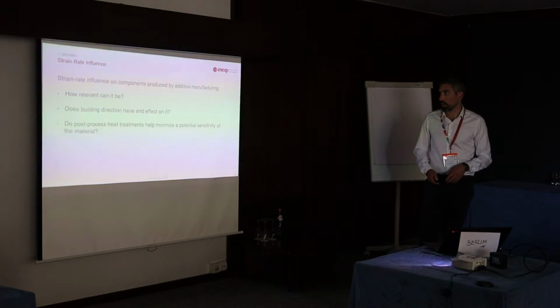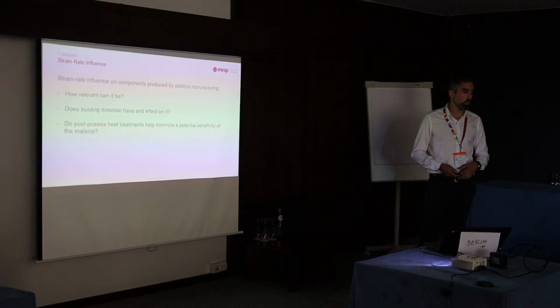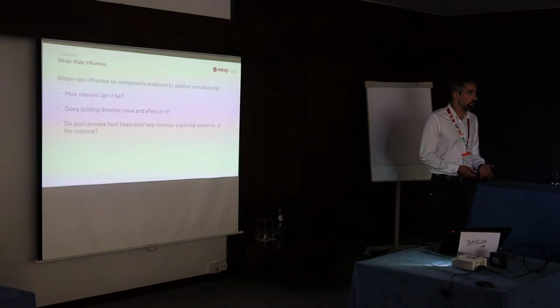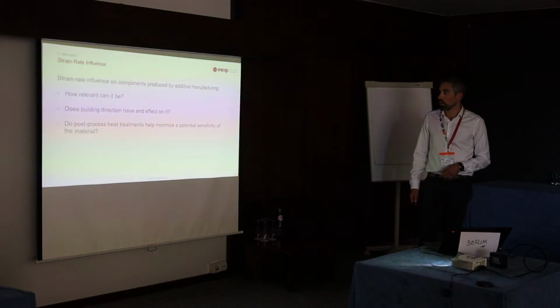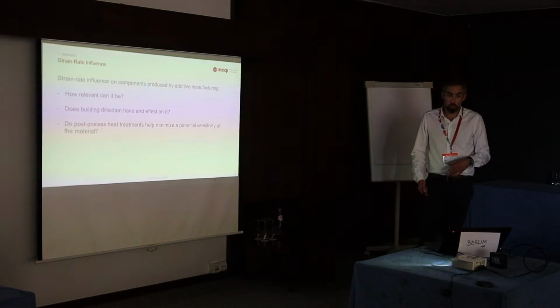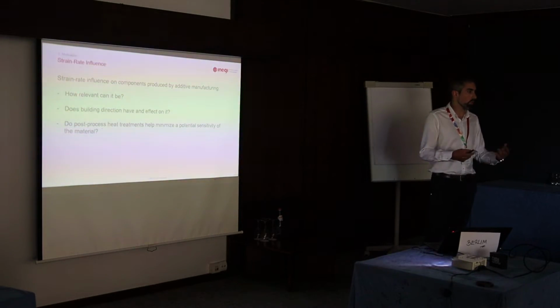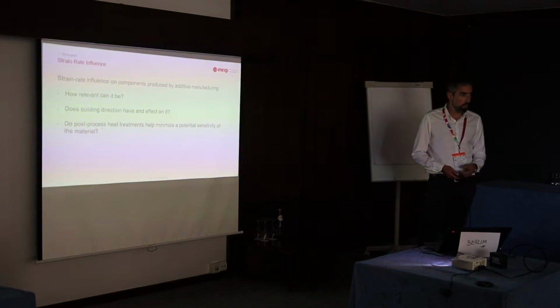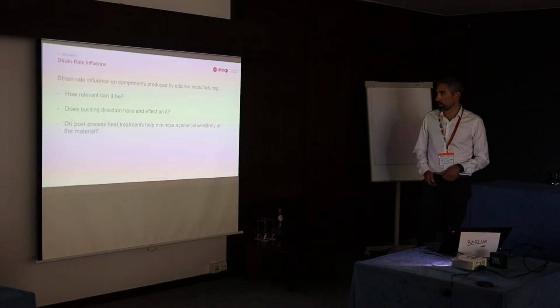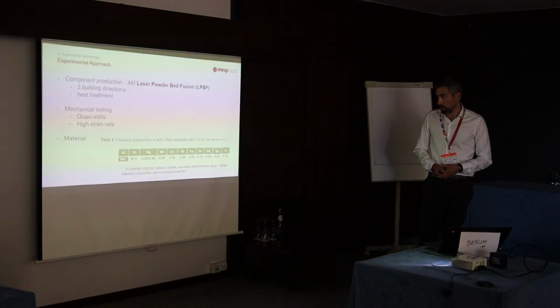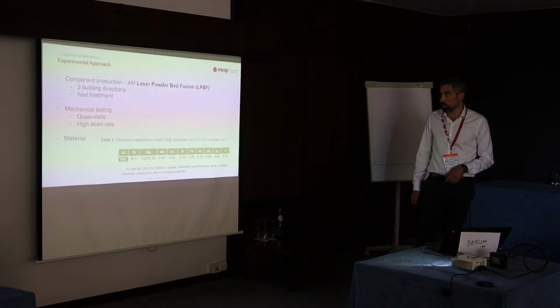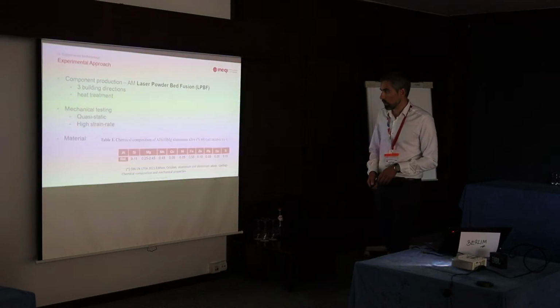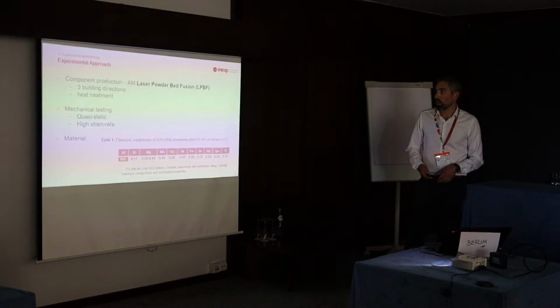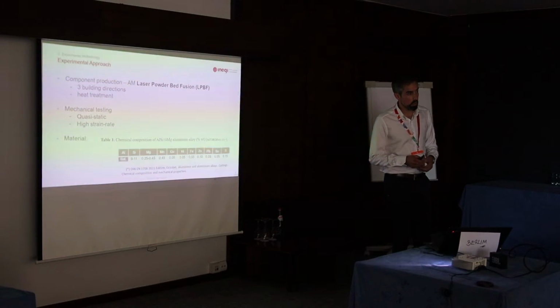So we wanted to understand if and how the building direction would influence. We know that it has influence, of course, on how the material settles in the end, and how a post-process heat treatment could help or not, if it would be cost-effective, let's say, or if it would be reasonable to apply it, if the gain would be considerable or not. So basically, we tested the three building directions. And we used heat treatment after that for each of the three building directions in order to compare with not heat treated, and also we tested at quasi-static and at high strain rate and very thin specimens.